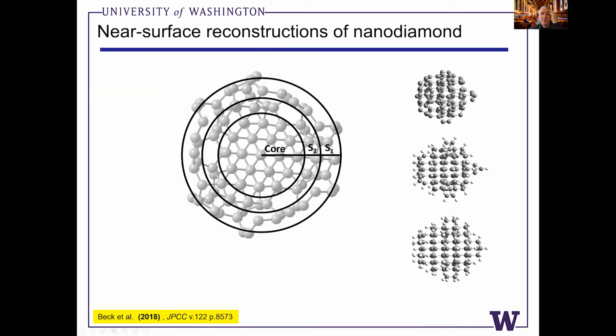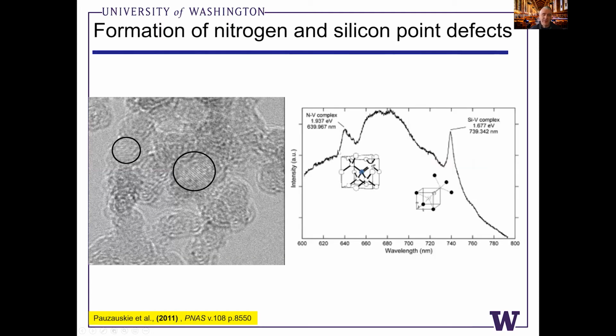In this paper, we did some calculations of how many layers do you have to go from the surface into the core to really identify a diamond phase. And there are indeed several, at least monolayers of reconstructed surface atoms that are forming kind of a combination of sp2 and sp3 bonds. And we think this explains some of the pre-edge X-ray absorption spectra.